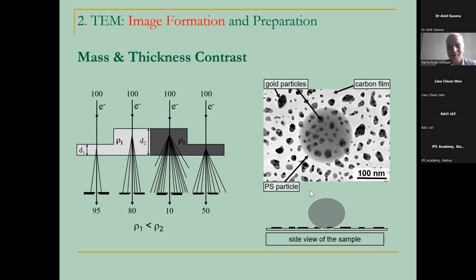And in this situation, as depicted here, we have the polystyrene particle, an organic particle. The density of the organic particle is of course very low, but still it contributes significantly to the thickness of the substance. Therefore, because of the higher thickness of this region, this area appears much darker. This is the thicker area, and these particles are the denser particles inside the thicker areas. So in this case, if we have the idea of the density of the materials in the heterogeneous substances, then we can estimate how the substances are imaged in transmission electron micrograph.